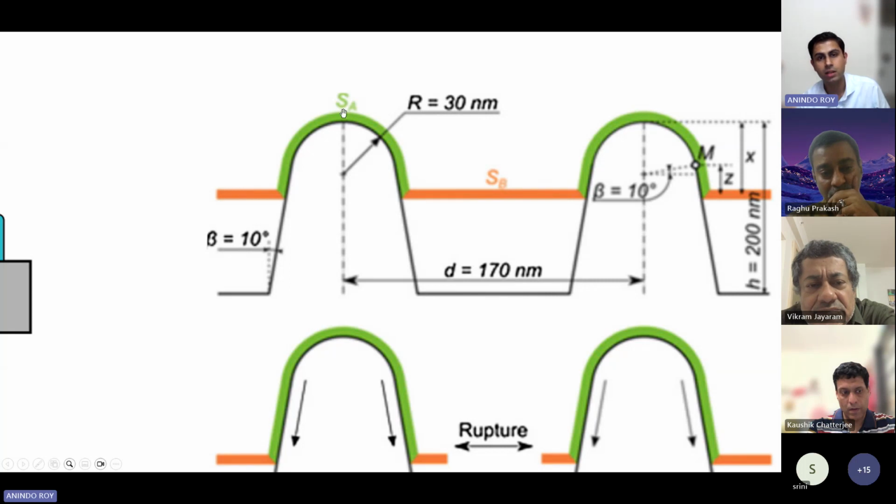Because this point is now fixed. This point initially, when the bacteria comes and attaches, that point becomes fixed. It cannot now move around. So therefore, let's say this was 1 unit, and after stretching, this has now become 1.5 units. So that 0.5 unit increase has to come from the region that was initially suspended between the pillars.